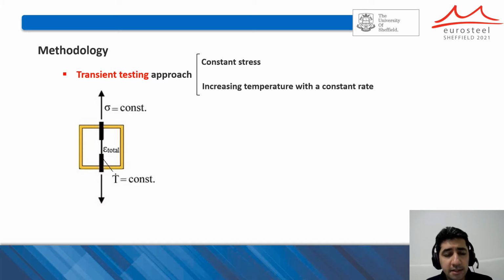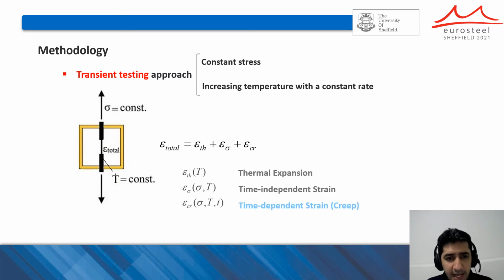As to the methodology of this study, the transient state testing approach was used. In this method, the material sample is first loaded to the desired stress level, then while the stress is kept unchanged, the temperature is gradually increased with a constant rate until failure occurs in the material. And during the test, the total strain within the gauge length of the sample is measured using an extensometer.